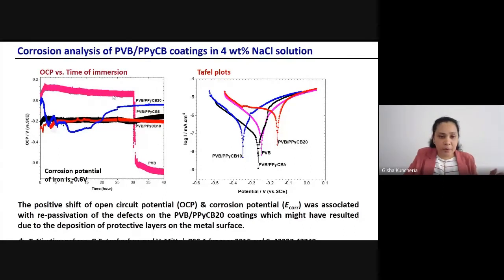But this is a barrier protection, simple barrier. If any defect occurs on the polymer coating, there is no more protection. So till 30 hours, it gives the protection. But after that, there is a sudden decrease and it reaches minus 0.6. After that, you can see the potential is no more increasing. So there is no more protection, and corrosion of the metal has started.